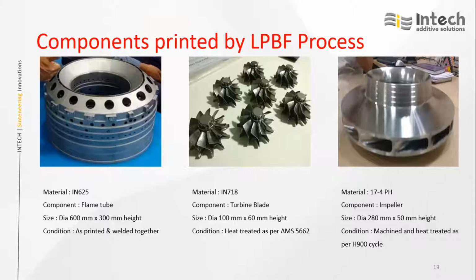And this is the impeller, on the right hand side, which is made of 17-4 PH material. It has a diameter of 280 mm and 50 mm height. Machined and heat treated as per H900 cycle.